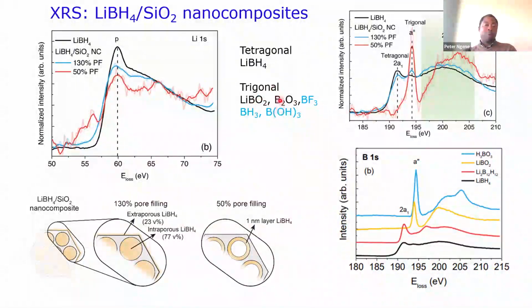And this trigonal boron is like LiBO2, B2O3, and BF3, or BH3, or even B(OH)3. So initially, when we did this for the hydrogen storage, we thought, okay, we are forming lithium borates, which one of the referees actually concluded, which we knew it was not. But in this case, we are sure there is no oxidation. We did this experiment several times.